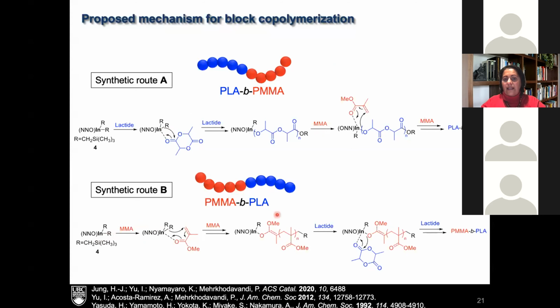And then here you have an alkoxide, which can then carry on an insertion reaction, and you can go ahead and do lactide polymerization. So the initiation efficiency for either of these systems is not good, because that TMS methylene is not a good initiator in either case, but it's just good enough to get both of those reactions to work. And that's the key to this chemistry, I think.